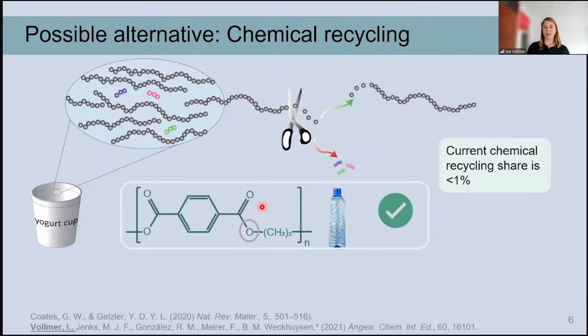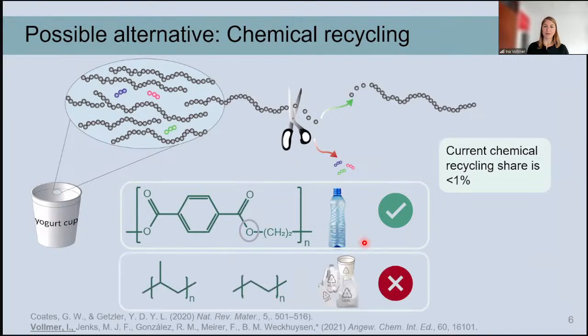And this works rather well for polymers with a heteroatom in the backbone. So this is kind of a weak link where you can break the polymer into its constituent monomers. And this is the case, for example, for polyethylene terephthalate, or PET, which we know very well from drinking bottles. However, there are also polyolefins, polyethylene and polypropylene, which do not have such a weak link in their backbone, but just the same kind of carbon-carbon bond all along the chain of the polymer. And so there is no weak link where we can selectively break the polymer into its monomers.